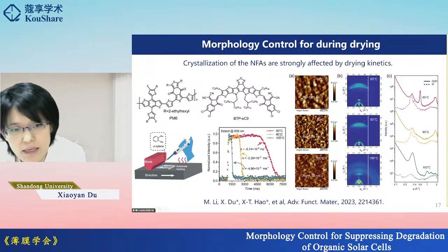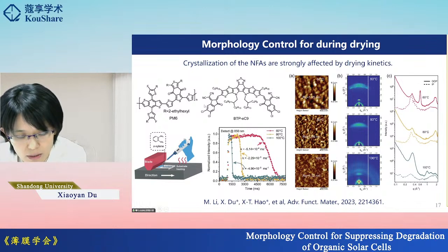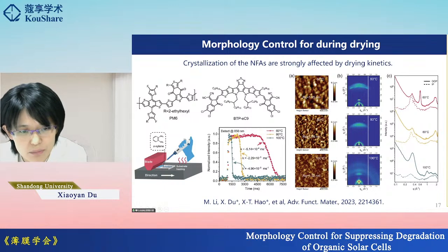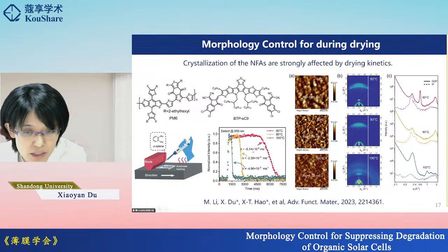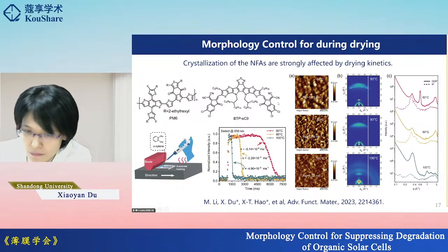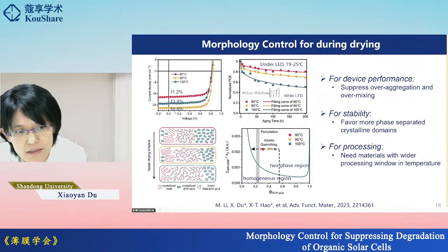Another example we show here highlights the need for a wider processing window during coating for these non-fullerene acceptors. Here, again with the scalable blade coating method, if we only change the coating temperature, the drying kinetics change significantly, which again influences the crystallization of these blends. For device performance, what we need is a medium state as shown here schematically. So we need to suppress the over-crystallization of the non-fullerene acceptors in slow drying, and also suppress the over-mixing in fast drying kinetics.